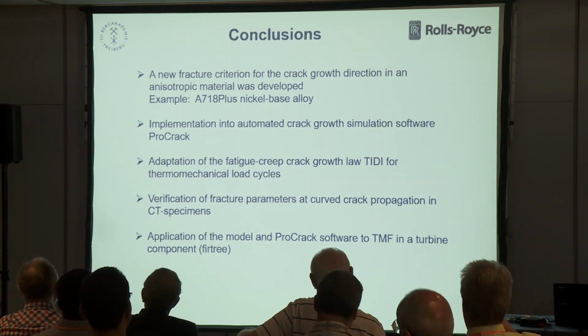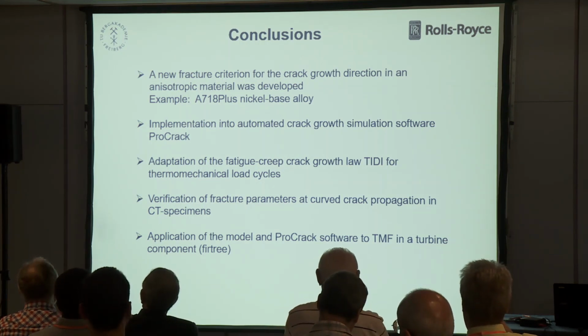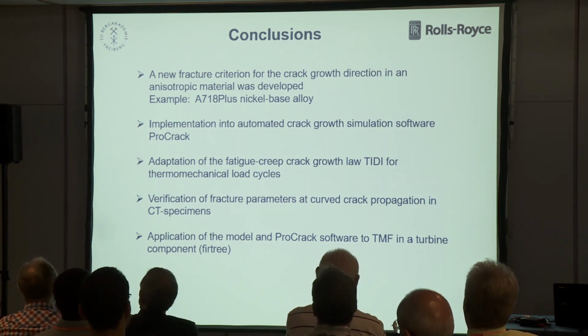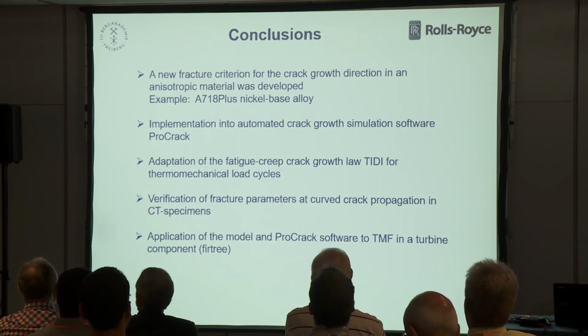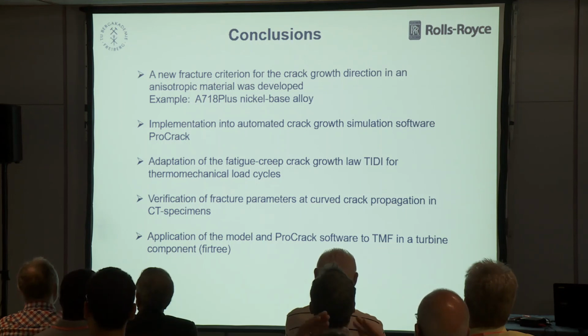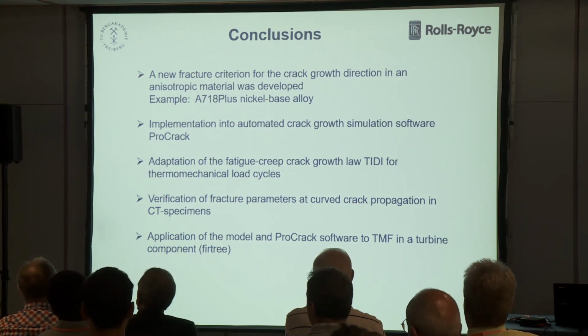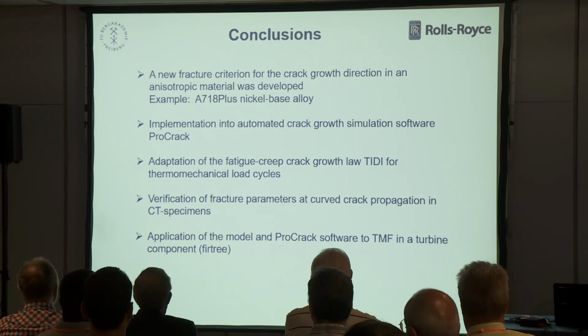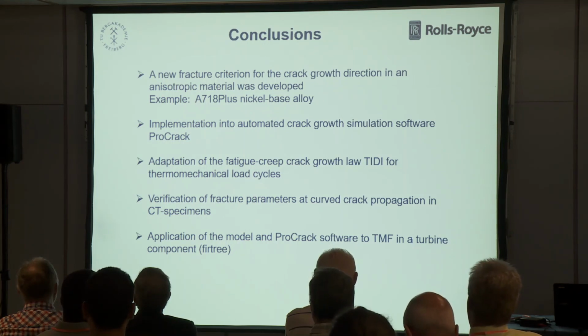This criterion was implemented in our code ProCrack, and also the TMF crack growth law was especially adjusted, and we could identify the parameters for this new criterion and crack growth law by means of specimen experiments, and finally apply it to the TMF of the special turbine component.